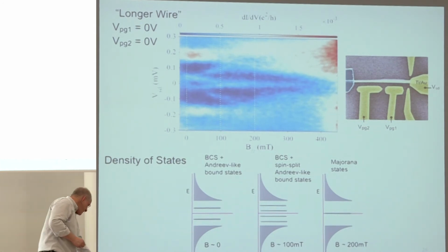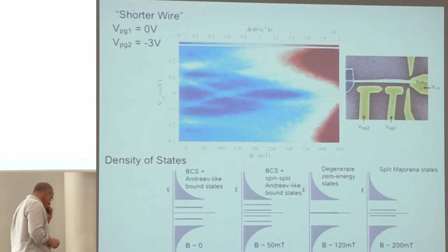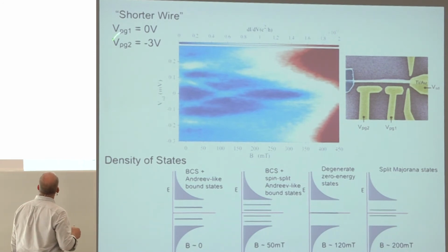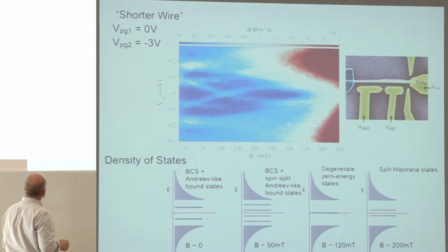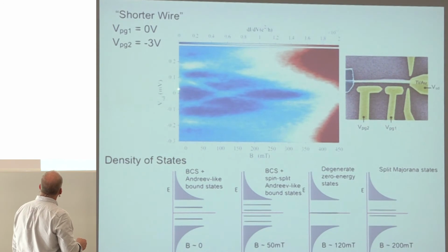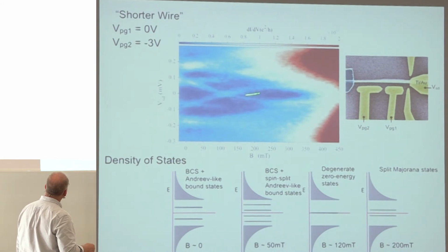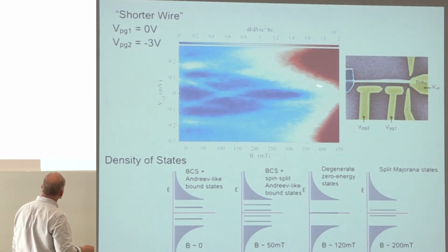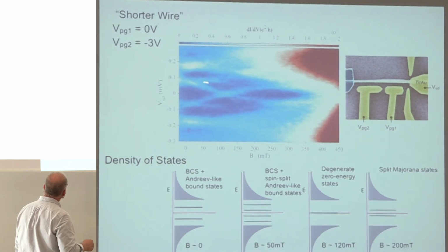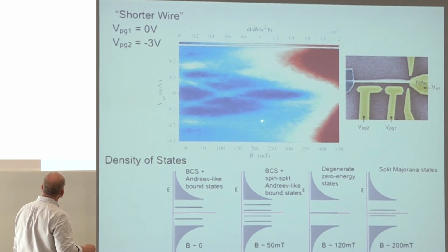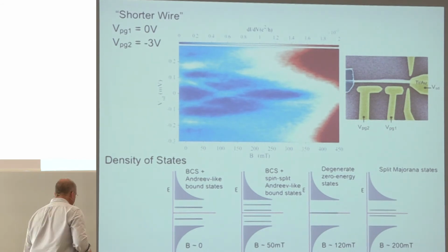Now, when I shorten the wire by putting this gate voltage at -3 volts, the character looks different. There's still a subgap state, but now these two levels don't go to the middle and meet. Instead, they appear to cross through each other, go back around, and just coincident with the destruction of superconductivity, they come back around again as if they're going to go for another lap. This one moves up into the continuum, while those two move back and forth.